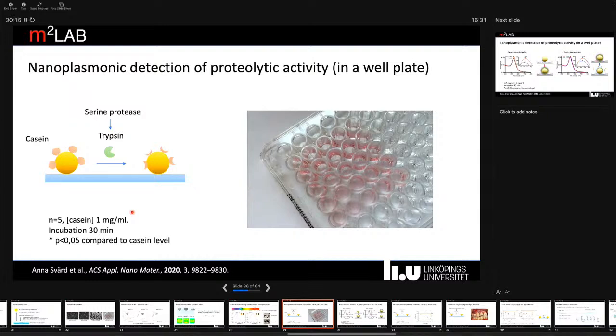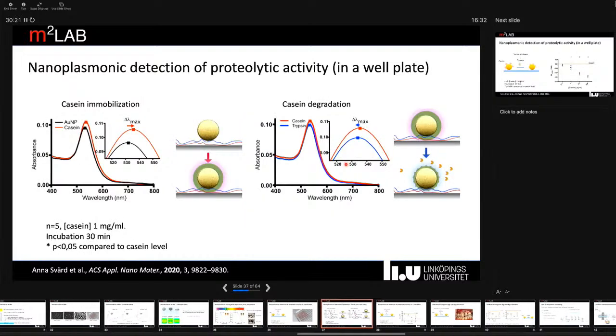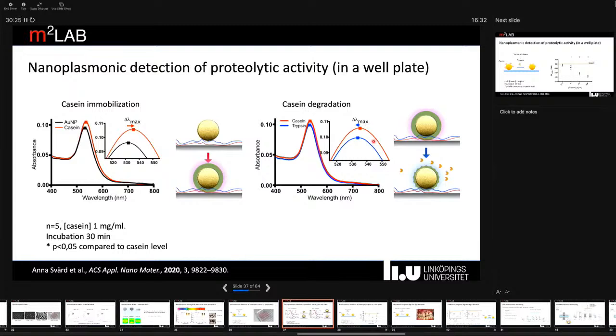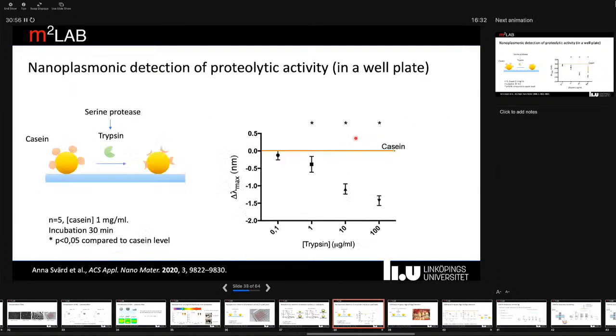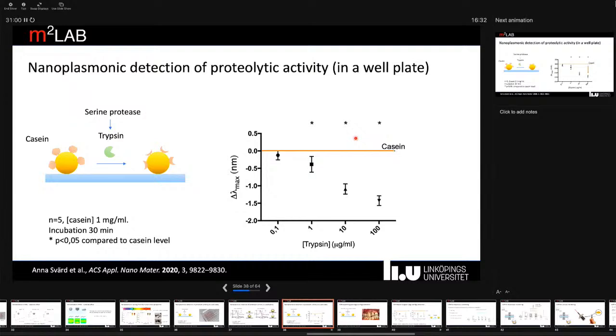So a very simple setup, and then exposing these sensors to trypsin, we can see that we get in this case a blue shift of the plasmon band. So this shows the LSPR band during the casein immobilization or functionalization of the particles with casein. We have a red shift, and when we degrade the casein, we remove, of course, mass from the surface, which we see as a slight change in the LSPR band and intensity. But sufficiently large to see this quite clearly with a plate reader. And using this simple strategy, we can detect fairly low concentrations of trypsin.